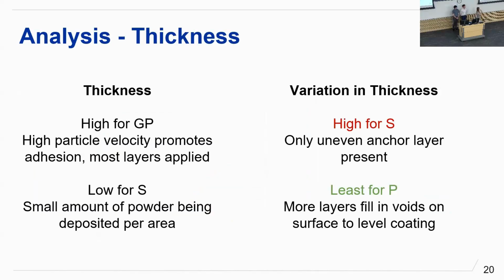So a little bit of analysis on this. We attributed the high thickness for the high gas flow rate and passes to a high enough particle velocity that adhesion is encouraged, and there are enough layers applied onto the coating that it levels out and makes it thick. And we attributed the low thickness for high stage speed to the small amount of powder being deposited on each area at one time per pass.